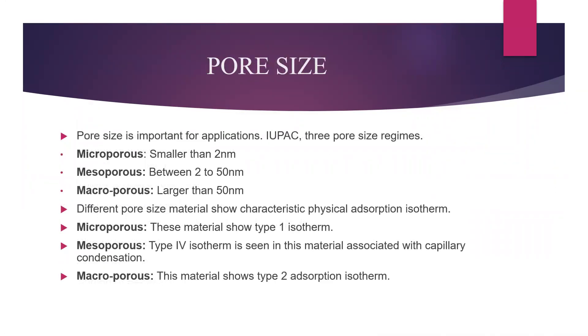Pore size is important for applications. IUPAC defines three pore size regimes: microporous (smaller than 2 nanometers), mesoporous (between 2 to 50 nanometers), and macroporous (larger than 50 nanometers). Different pore size materials show characteristic physical adsorption isotherms: microporous materials show type 1 isotherm, mesoporous materials show type 4 isotherm associated with capillary condensation, and macroporous materials show type 2 adsorption isotherm.